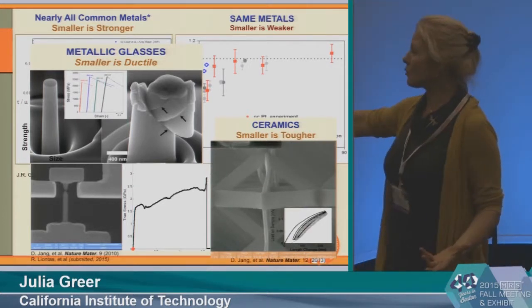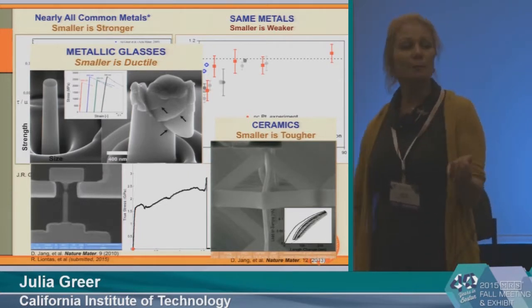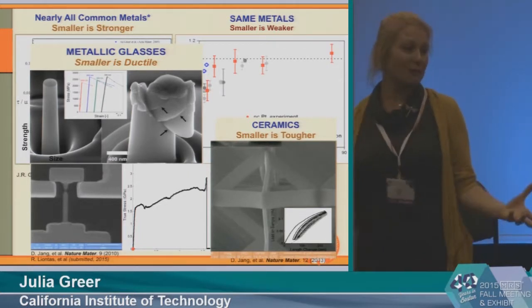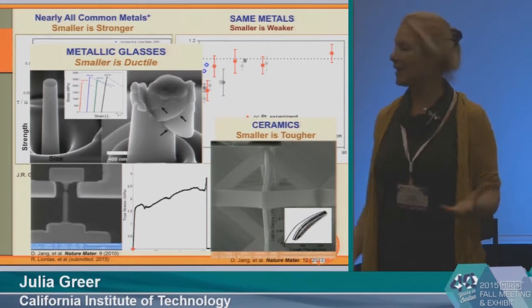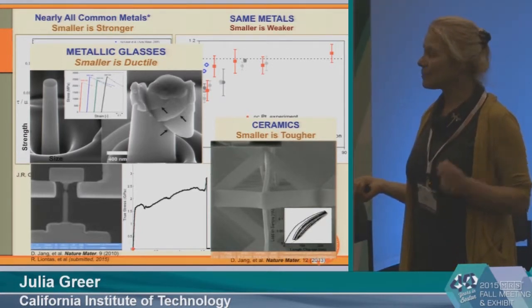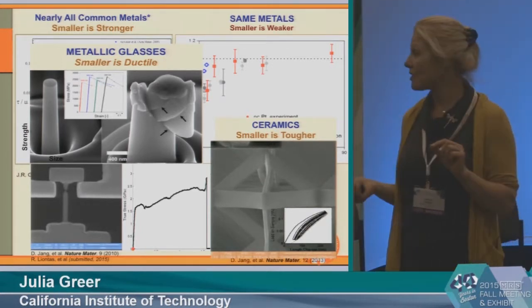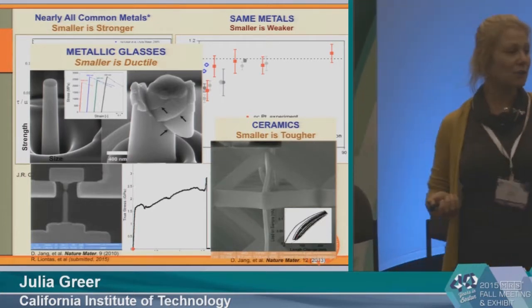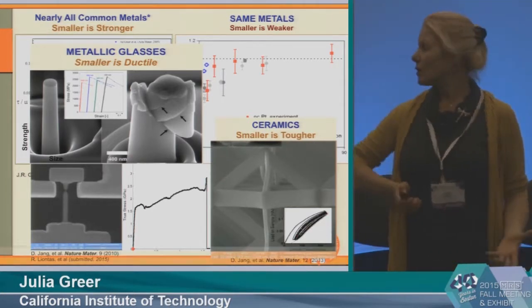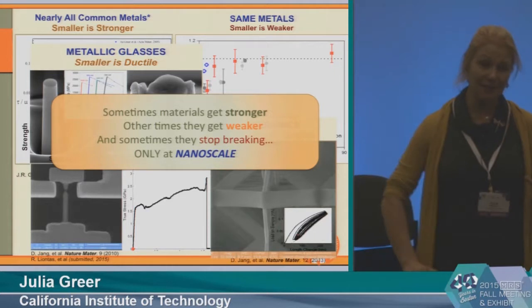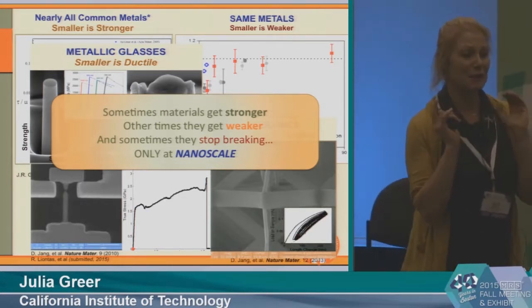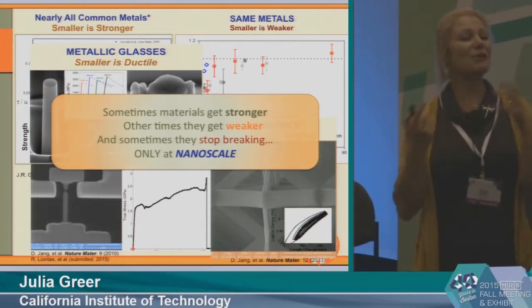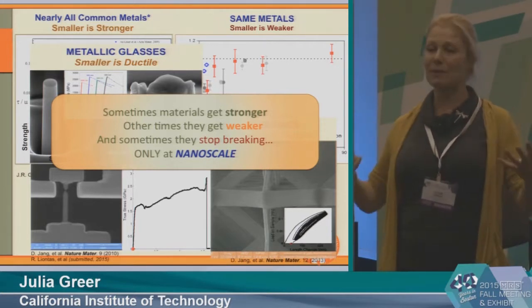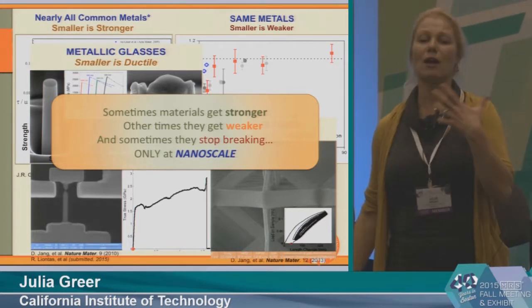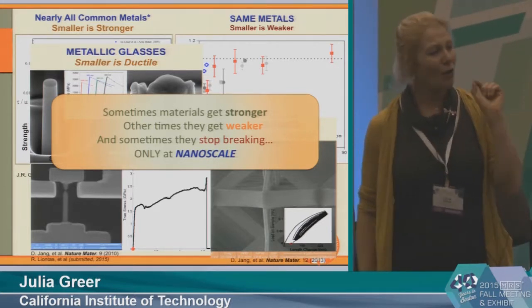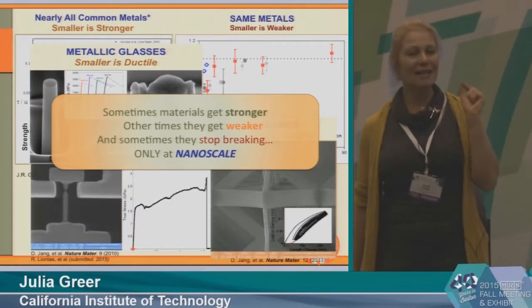So this tensile stress component here exceeds 2 GPa. So at this point, most ceramics would absolutely fail, brittly fail. And you can see that these nanotrusses, whose dimensions are 75 nanometers, are able to deform over multiple cycles without any kind of failure. So the takeaway message here is this. Sometimes materials get stronger. Sometimes materials get weaker, and sometimes we can stop them from breaking. These are all very unusual, upside-down properties. But all of these properties emerge only at the nanoscale.